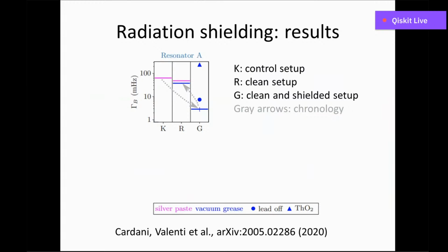As a control, in this same setup, we can first remove the lead bricks surrounding the cryostat, shown by the circle, which will increase the burst rate. And we can add a thorium source, radioactive source, close to the cryostat, which will then bring the burst rate to values that are above the ones measured in the unclean and unshielded setup, which really convinces us that these bursts are radioactivity related. When we measure, finally, in the clean setup, we see that there is an improvement with respect to the uncleaned, but we also see that shielding in the mountain plays a great role in reducing the burst rate. And we can appreciate that using vacuum grease instead of silver paste, vacuum grease being more radio pure, has also a small but visible beneficial effect.